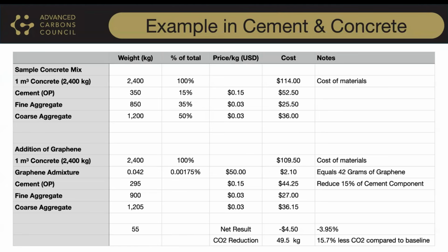But let's just focus on the CO2 reduction. The cement, of course, is almost entirely responsible for the CO2 footprint for concrete. So now we're removing the cement portion from 350 kilograms to 295 kilograms. The fine aggregate goes up to 900, and the coarse aggregate goes up to 1,205 kilos, so that we get our total original weight there.